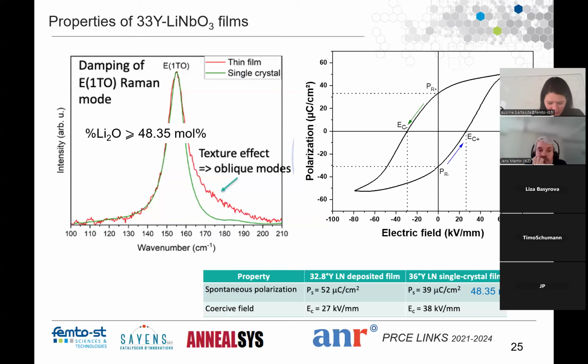When we measure the Raman spectra on these films, we get to the case where the films are textured, so we don't have in-plane orientation, and Raman spectroscopy is very sensitive to that, because the films have a tilted orientation of the polar axis, the z-axis, which is at 57 degrees. So basically, we have oblique mode presence, which means that in a single crystal I can properly separate parallel and cross polarizations. But in a thin film, I cannot do polarization separation. I cannot separate these modes properly because the film doesn't have in-plane orientation. So basically, I also have the oblique mode presence.